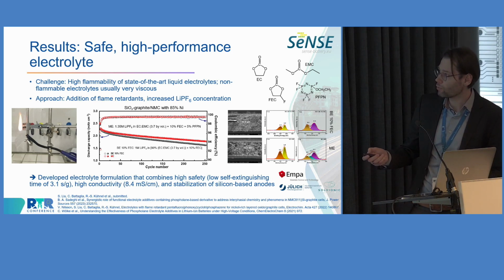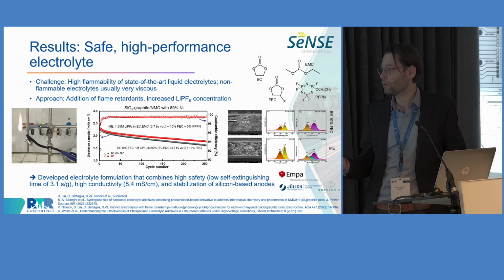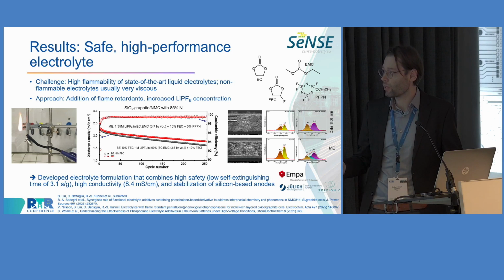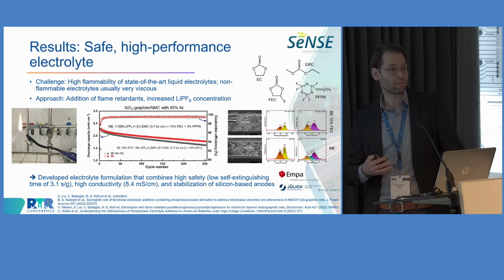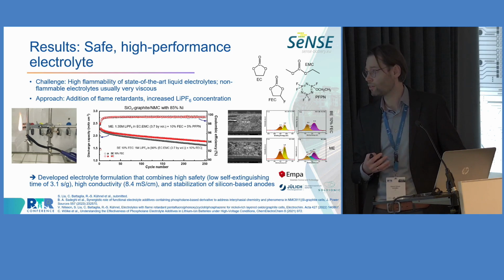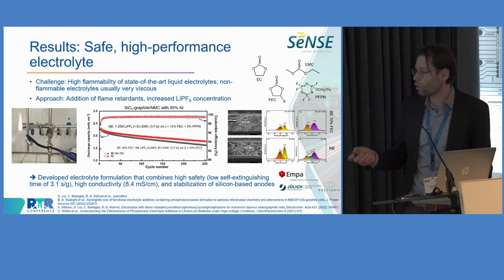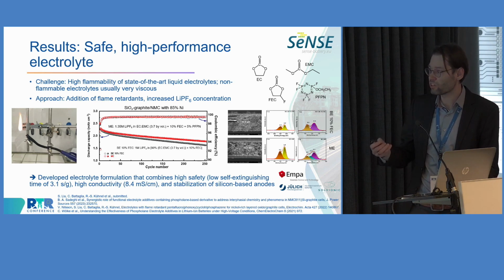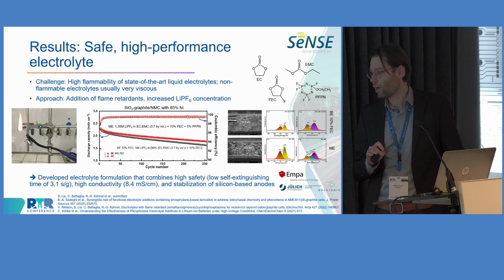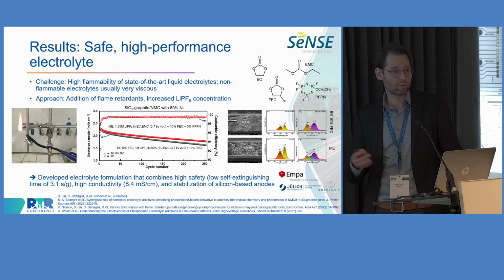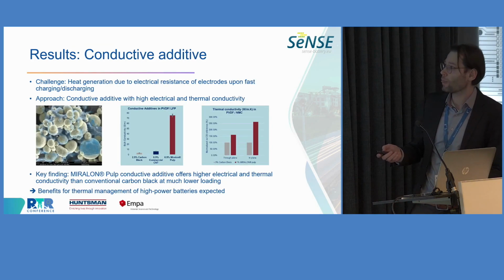And as you can see here, in that case, a silicon oxide graphite anode coupled with NMC, with a high nickel content also, we can really improve the cycling stability compared to a state-of-the-art electrolyte containing 10% FEC, which is another additive that is well known to stabilize silicon anodes. We also looked into the stabilization mechanism. I cannot go into the details now, and I think the paper will be out maybe latest in a few months. It's under review at the moment.